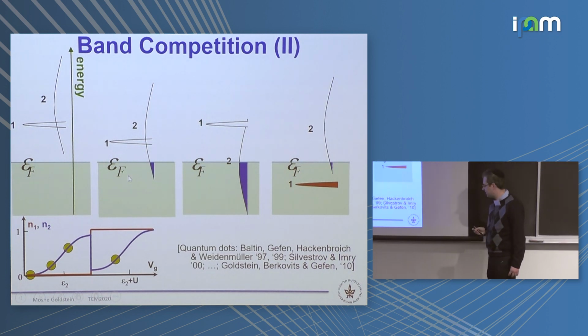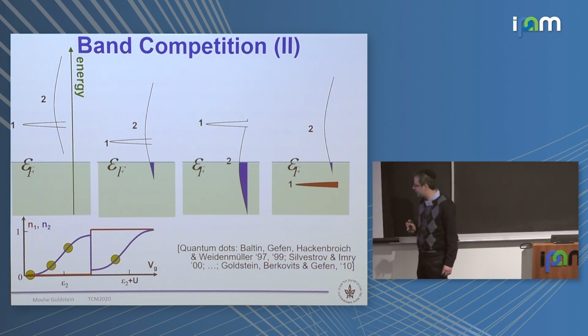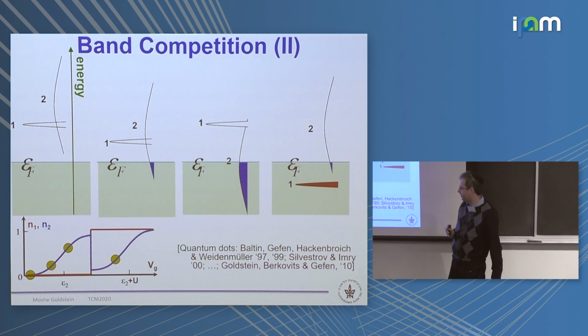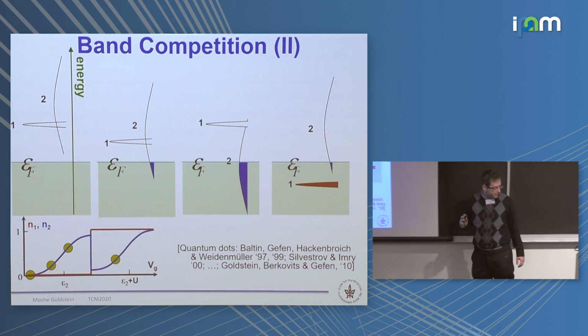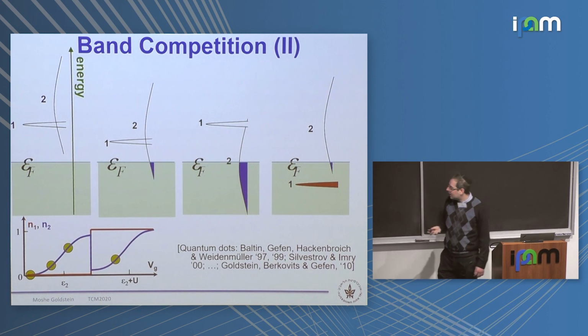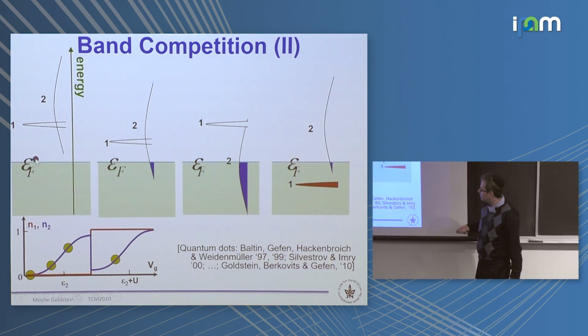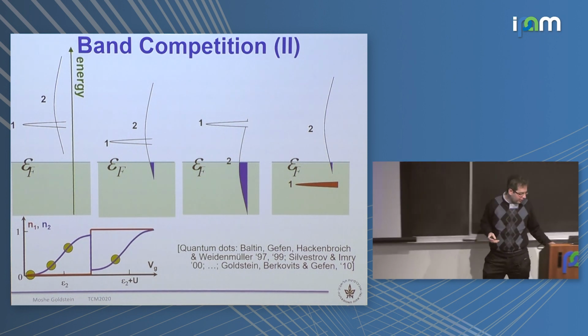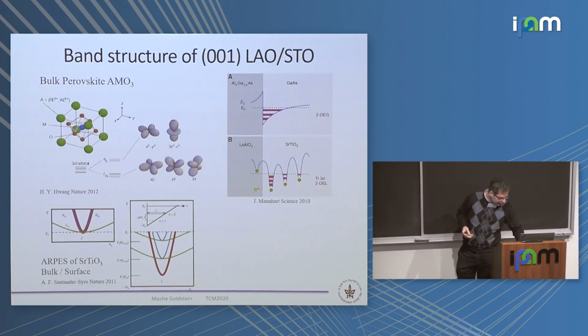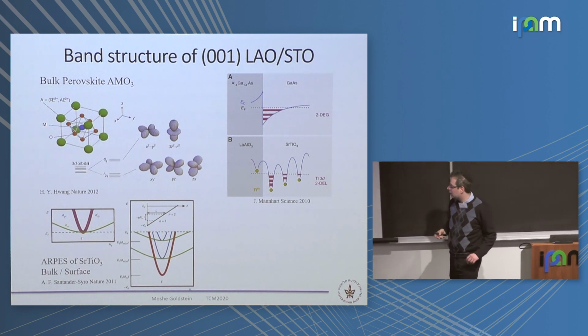So we believe that this is the basis, based on the Shubnikov-de Haas, this is the basis of what is happening in our system. Just that in our system, it's a bit more complicated version of that. And the reason is that we don't have just one band with always high mass and one band with lower mass. They are more complicated, and the density of states are changing as a function of the Fermi energy. So we needed to do a better modeling.